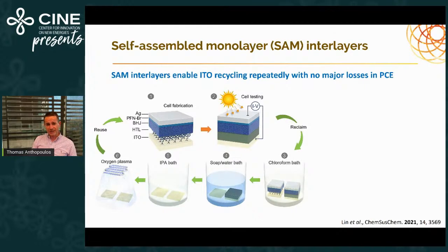One of the most interesting findings from that study is that we can take these devices, which are highly efficient, over 18%, use them, and then reclaim part of the device, specifically the ITO substrate. How do we do that? We dip the whole device in chloroform, we remove the organic and the top layer, then we soak in a water bath to remove the PSS, an IPA bath to clean all the residues, and oxygen plasma to burn away any organics, including the self-assembled monolayer. And then we take that plastic or glass ITO substrate, refunctionalize with a new SAM, deposit the bulk heterojunction, complete the device fabrication, and test it.